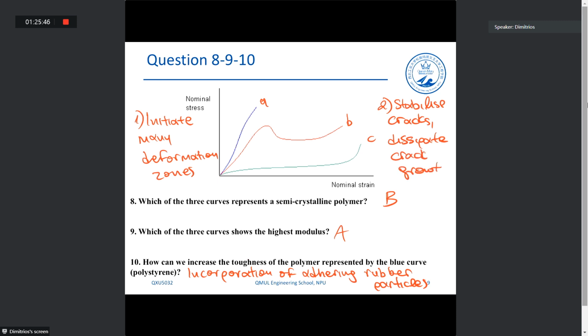Indeed, I saw a couple of you mention the increase of temperature or decrease of strain rate. It can be a way to achieve that, but overall it will not achieve as high toughness as the incorporation of rubber nanoparticles, because still the chains in this case are highly entangled, okay? And the entanglements will be causing us significant problems even if we supply a certain amount of thermal energy to the chain. But yes, certainly increase of temperature can be considered as a correct answer.